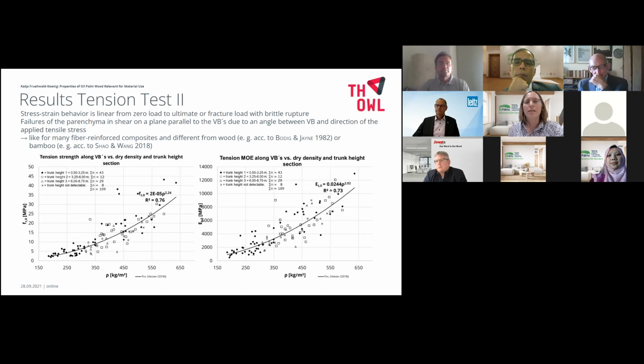This is due to the anatomical structure. Like for most long fiber reinforced composites, the Young's modulus and strength in tension parallel to the vascular bundles is high and depends on the density and the properties of the vascular bundles. Like for many fiber reinforced composite materials, the stress-strain behavior in the test parallel is linear from zero load to the ultimate or fracture load. This is typical for wood in tension as well. All failures were due to an angle between the vascular bundles and the direction of the applied tensile stress. The macroscopic fracture patterns differ significantly from those for softwoods and hardwoods or bamboo.